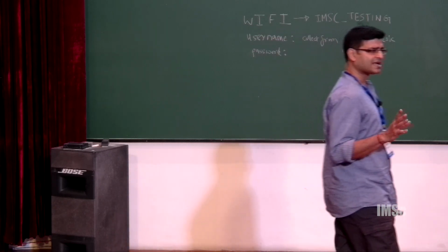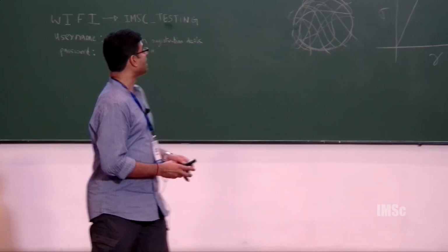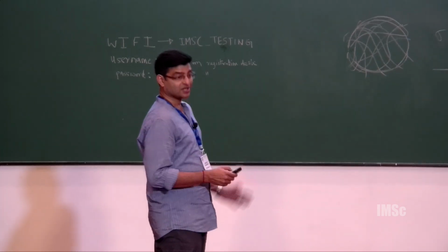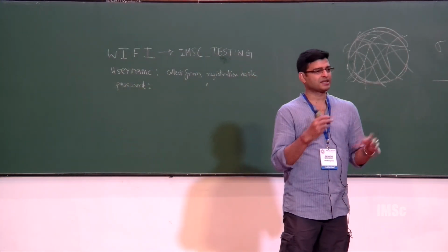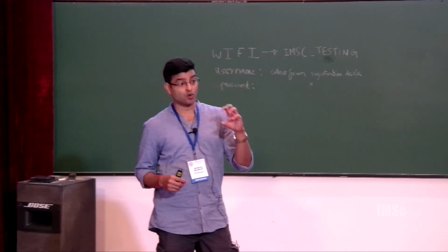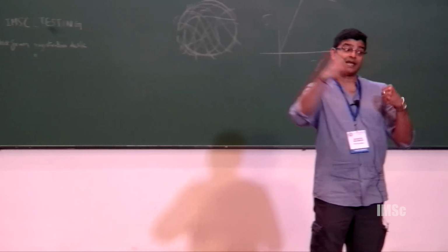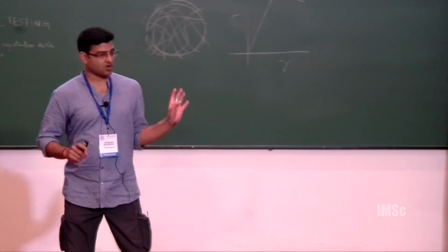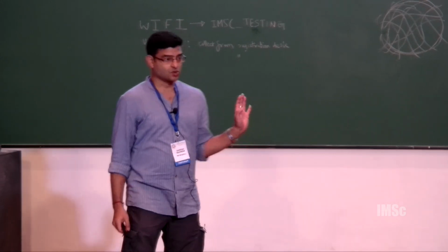The dry particle size is around 430 nanometers or so. They swell because the polymers remain soluble below that temperature, but beyond that the hydrophobic domains open up, and there is a competition between hydrogen bonds, and the particles also undergo some collapse state. Very interestingly, you can form a gel-like network because of this. But in the state where the polymers are soluble, there is no such state. You can consider it to be typically a hard sphere, because with salt there is no effect at all.